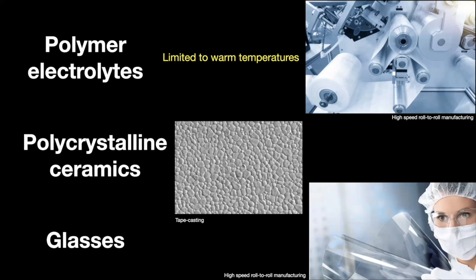There are some polymer electrolytes that have limited conductivity at room temperature, but typically the way you see that done is the addition of liquid to the polymer, in which case it is not solid state, and you start to bring in the same old problems that lithium metal batteries in the early days prior to lithium ion were exhibiting, which is safety problems. Polycrystalline ceramics certainly can block dendrites.